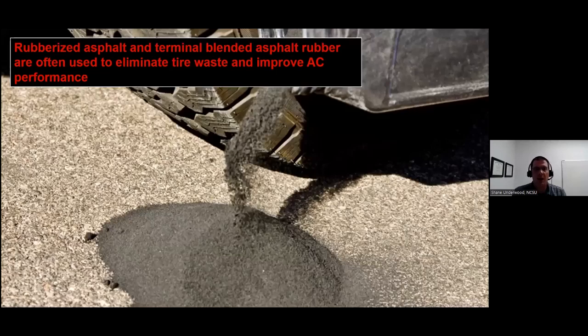Another material that we often use, this comes in and out of fashion every 10 years or so in the US, is rubberized asphalt binder and terminal blended asphalt rubber. We use these to eliminate tire waste. Generally, the beauty of using crumb rubber or rubberized asphalt is that it not only uses a waste stream, but unlike some potential for recycled materials, using this waste product actually improves the asphalt concrete itself. So it's a double benefit. You reduce environmental impacts, but you also create a longer lasting asphalt material.